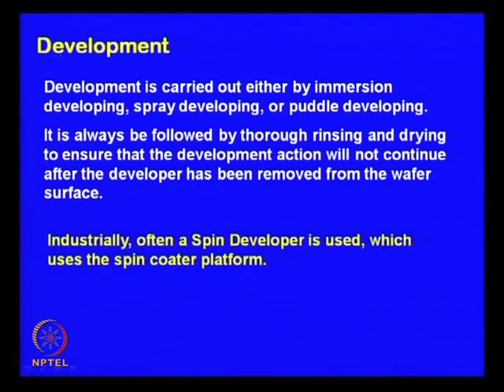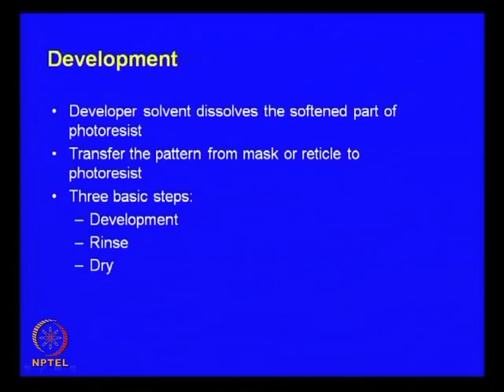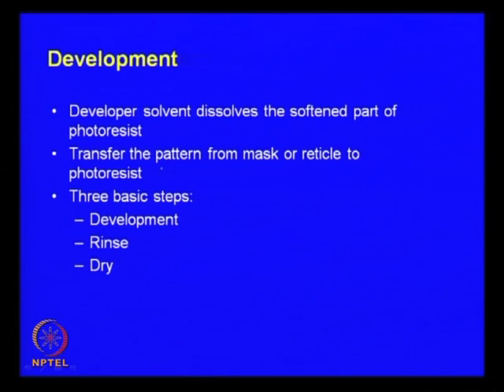Development is carried out either by immersion developing, spray developing or puddle developing. It is always followed by thorough rinsing and drying to ensure that the development action does not continue after the developer has been removed from the wafer surface. Industrially, a spin developer can also be used, which typically uses a spin coater platform. So, a development solvent dissolves the softened part of the photoresist and transfers the pattern from the mask or reticle to the photoresist, and the 3 basic steps are development, rinsing and drying. We will pick up the concluding part of photolithography in the subsequent class.